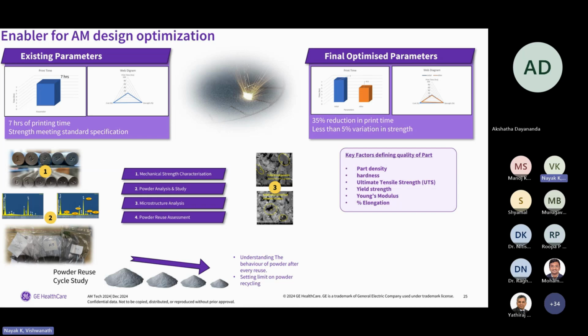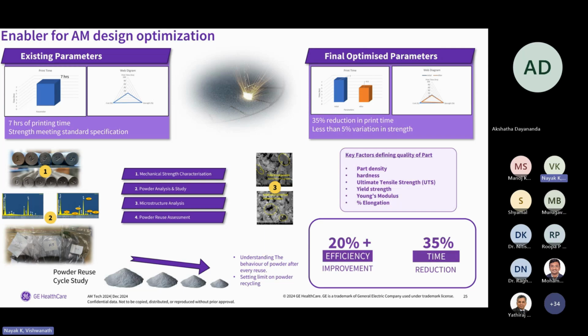Definitely this is a great achievement, where we typically see almost 50%. We saw about 35%. We could see about 45 to 50% in a scenario where the time can also reduce. So this is possible in additive, and this is directly proportional to the cost. It brought in 20% efficiency and a time reduction of 35%. So this is a significant factor to consider when you're designing additive and getting the best cost out of it, to keep improving over a period of time.